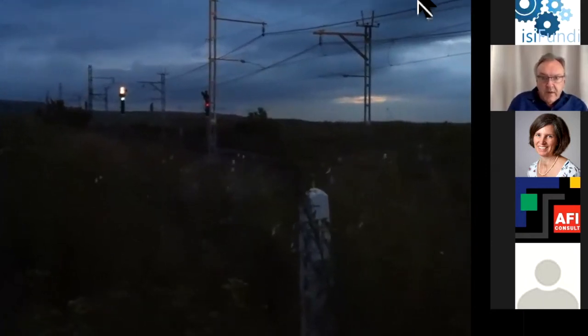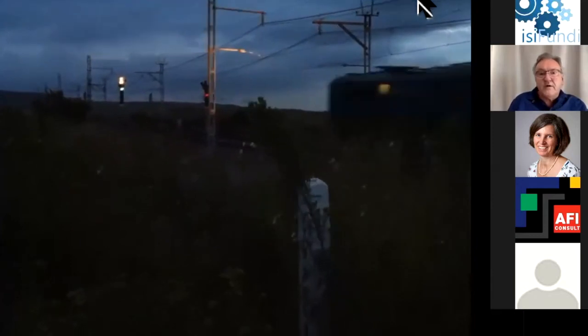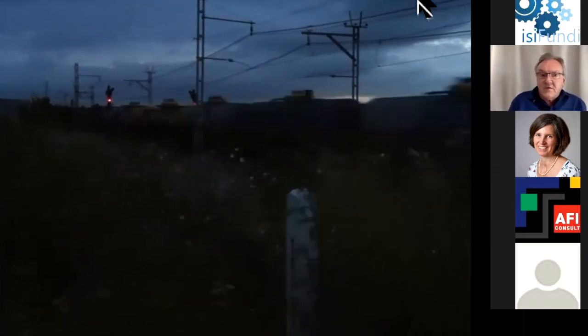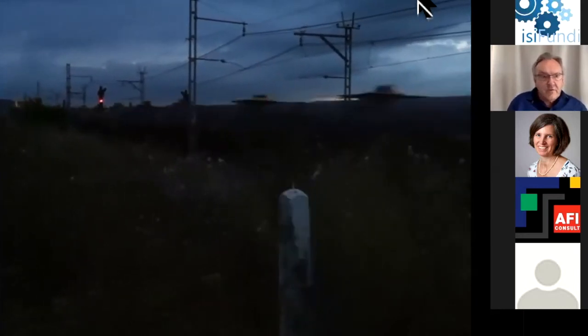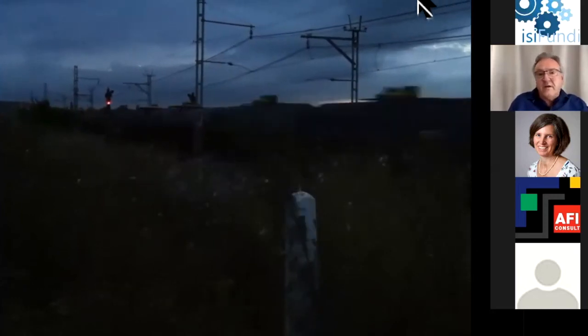And as we see this train moving past, you can see that there are 4 locos up front, which are drawing several thousand amps. If some of that current gets into the pipeline and then discharges on its way back to the traction substation, we can get catastrophic corrosion of the pipeline at the point of discharge.